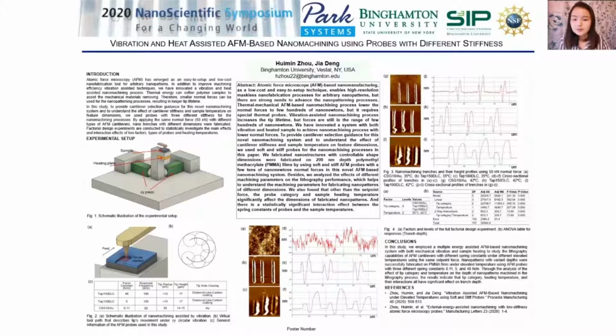And the last one is a very soft tip, CSG10 with gold coating. The spring constant is only 0.1 Newton per meter. So there are almost 500 times differences between the spring constant of the stiffest and the softest tip. Figure 3 shows the experimental results, including topography images of the lithography trenches and cross-sectional profiles of the images.